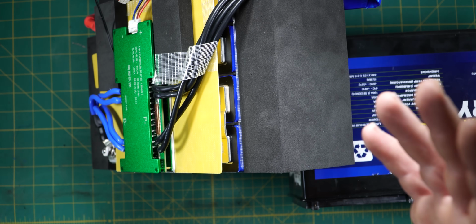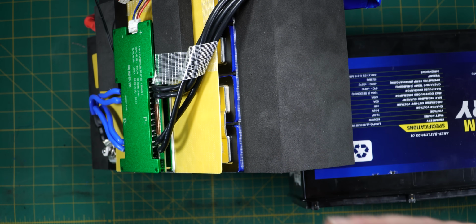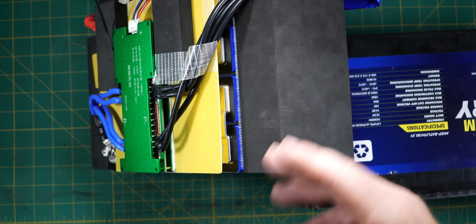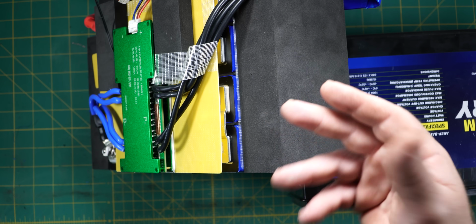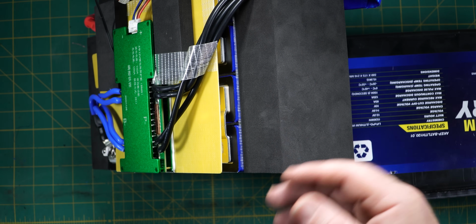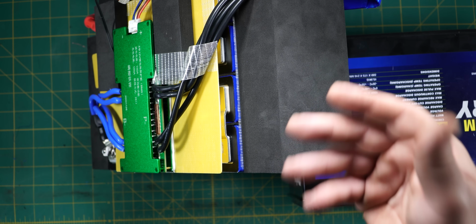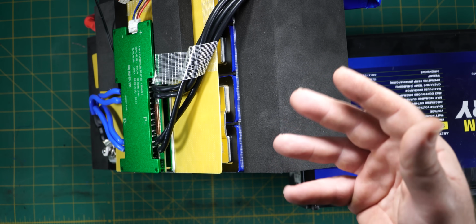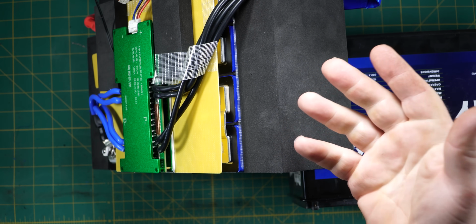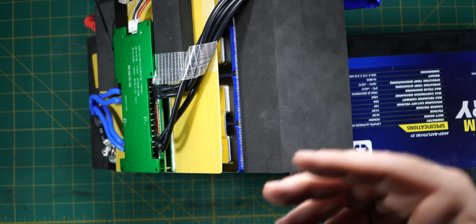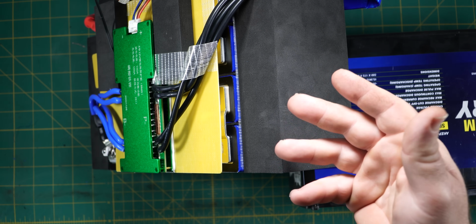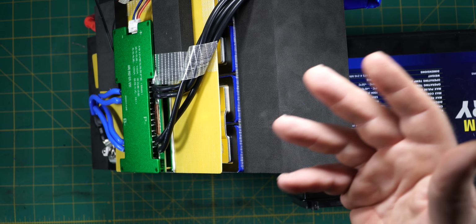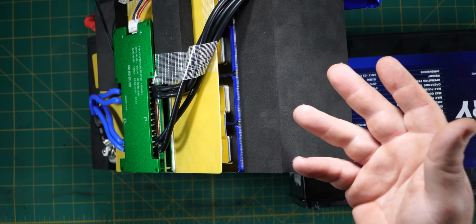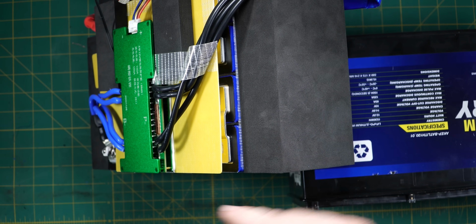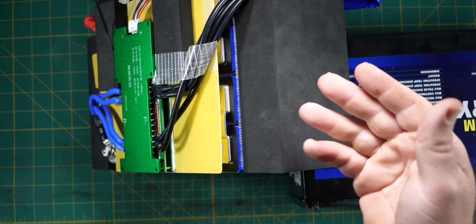Now, if we use our approximation for the current capability of aluminium, saying 2 amps of current capability over a short distance per millimeter squared of area, that would give us a current capability of that bus bar, if it's aluminium, of around about 114.4 amps, which, well, that's pretty close to 120 amps, remembering that everywhere in the circuit will be the same amount of current.